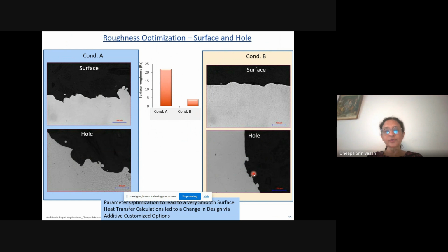I did mention to you earlier there's a direct energy deposition. The surface roughness is quite rough because it's a high throughput rate, larger powder particle sizes, and a much faster way of building the part, which necessitates further machining to the near net shape geometry.